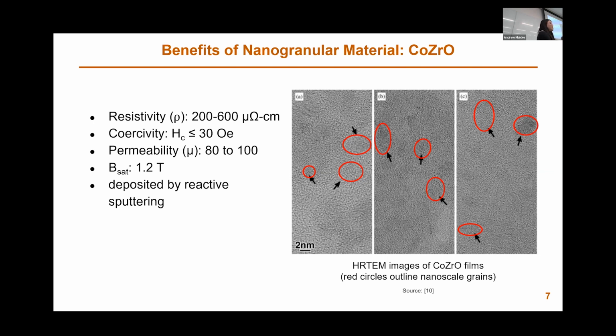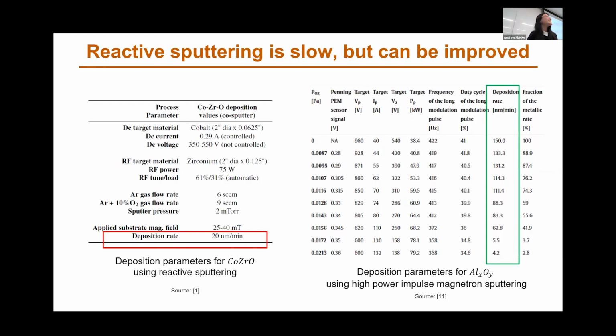You have these very small magnetic grains, nanoscale grains, inside this matrix of insulator. Cobalt zirconium oxide has, again, all the properties we like, and in particular, it's deposited by reactive sputtering, which is compatible with CMOS, but it is very slow. This particular group that did make on-chip inductors with cobalt zirconium oxide had a deposition rate of around 20 nanometers per minute, which is equivalent to 1.2 microns per hour. To give you a rough estimate, these inductors typically are like 40 microns thick. So it takes a very long time to grow these inductors.